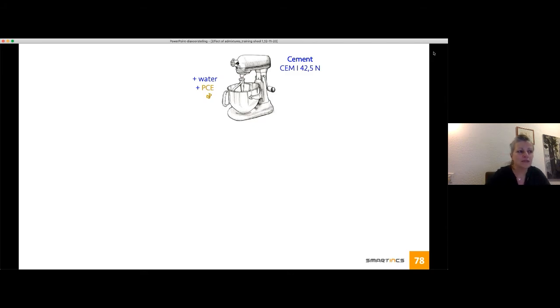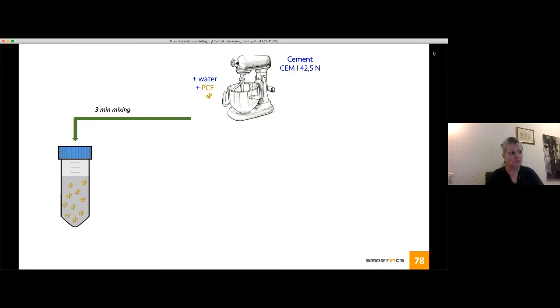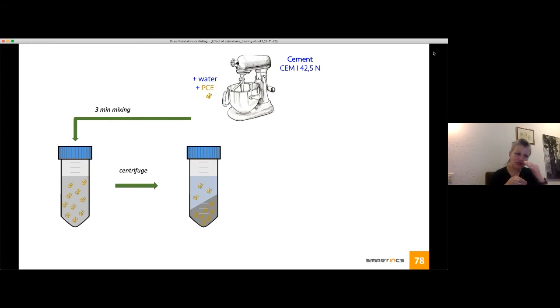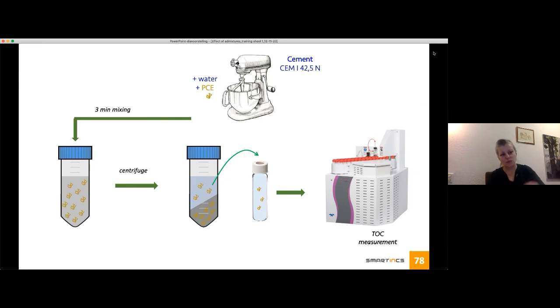How do we do this inside the lab? So we mix a cement paste in a traditional way with a Hobart mixer. Then you add your water and your admixture. And after 3 minutes mixing, we use a centrifuge tube. At that time, what you have is a cement paste, and inside your cement paste, you have your PCE. Then we do a centrifuge, and you will separate your solid from your liquid phase. What you will have in your solid phase is the PCE that is adsorbed. And what is in your pore solution? It's free, so it means it's PCE that is not adsorbed on the surface of your cement. And this part we will measure with a TOC.